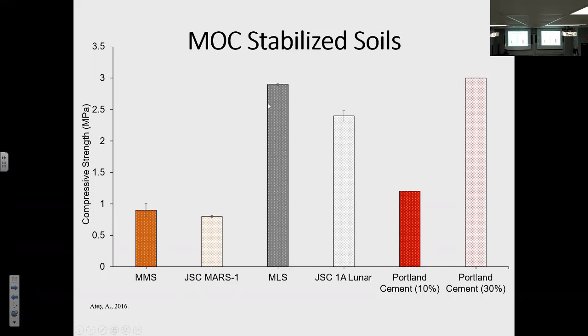The two gray bars right after that are the stabilized lunar simulants, and then the red bars are data from the literature about Portland cement stabilized soils at 10% by weight and 30% by weight. So first thing we noticed, we definitely saw some strength improvement. And some of the strength improvement for the Mars samples compare pretty well with the 10% Portland cement stabilized soils.